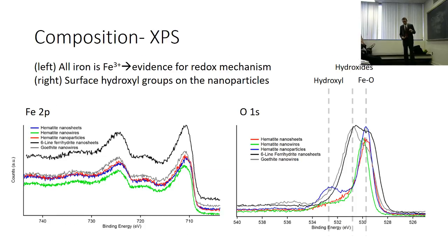Did XPS. XPS is another sort of characterization technique, a surface-sensitive technique. On the left, this is the iron part of the spectrum. The important takeaway is they all look alike. This is what iron plus 3 looks like, so this is more evidence for that redox mechanism. I put in iron plus 2, I got out iron plus 3. You have to have some oxidation event occurring.